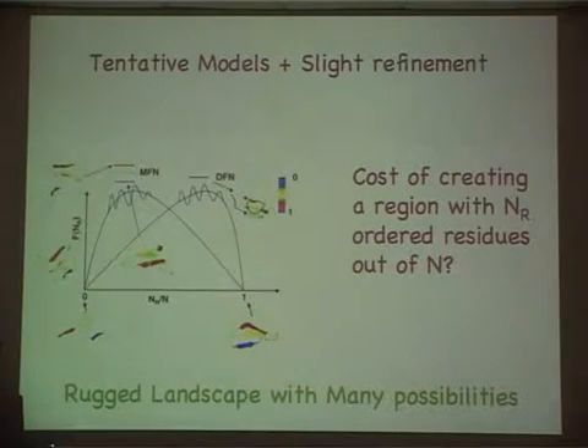That's the only requirement that I have, and I'll call it the multiple folded nucleus. This barrier is here shown to arise early in the folding process, which means if I sit here, the fraction of residues that are ordered is less than the fraction of residues that are ordered here, and this may correspond to some diffuse nuclei. For whatever reason, topological restrictions, the nucleus, in fact, forms only very close to the folded state. So these are all questions that people, in fact, want to ask.